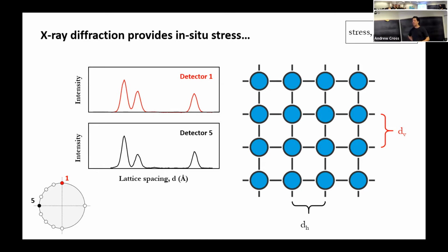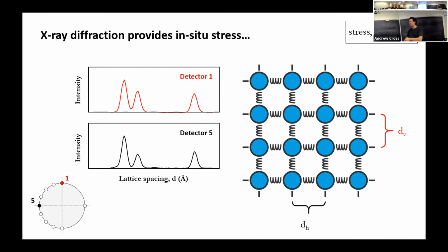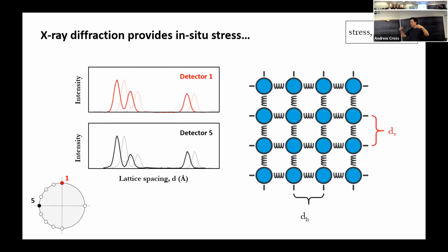And when it's just at room pressure and temperature, those spectra should look identical. Lattice spacing should be nice and even if we're looking at the same crystal plane. If we apply confining pressure now, so we're pushing on the crystal in equal amounts in all directions, we can think of each bond in that crystal lattice as a spring. So those springs are going to push together, and we'll get a shift of these XRD patterns towards smaller lattice spacing. So we're decreasing lattice spacing as we apply confining pressure.